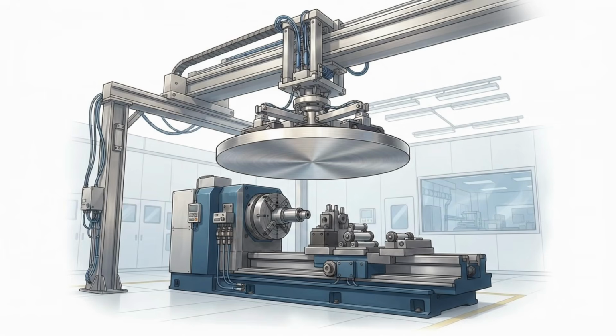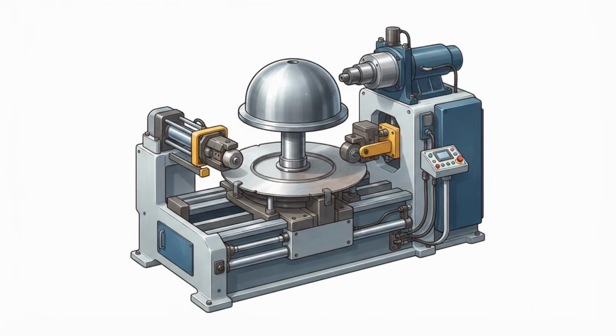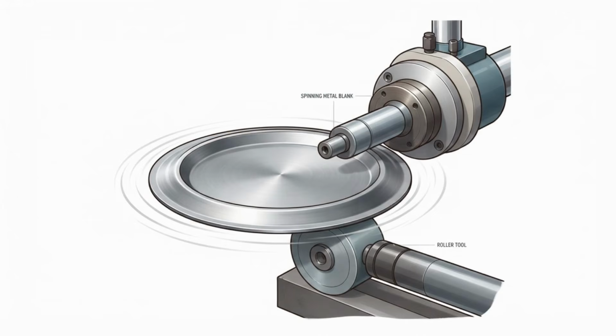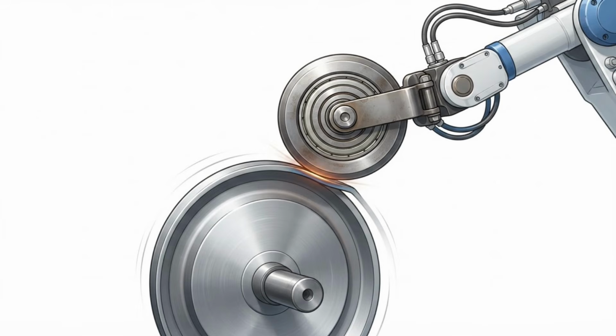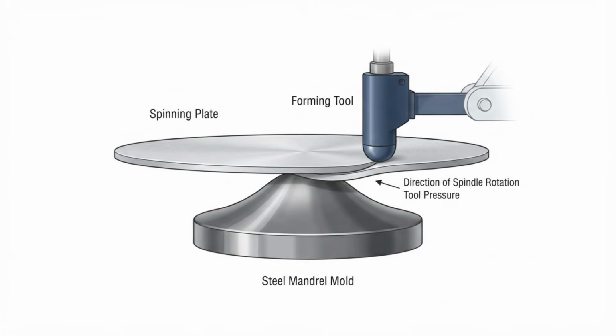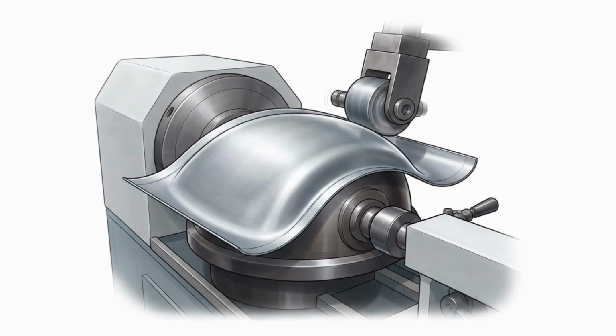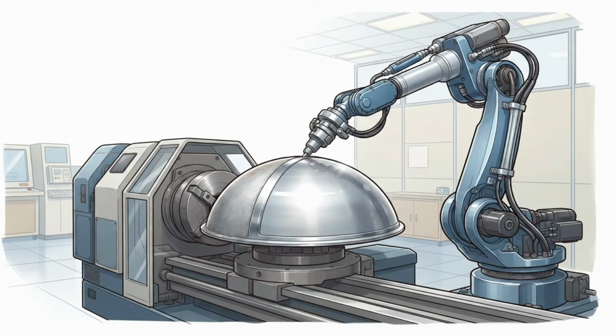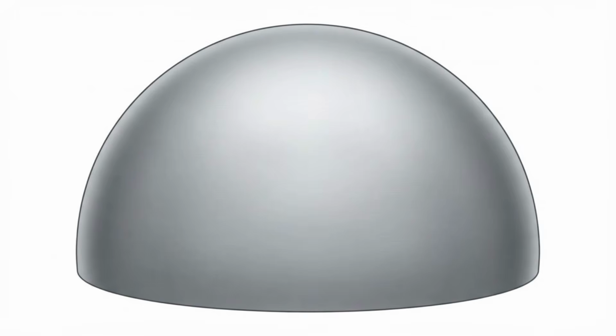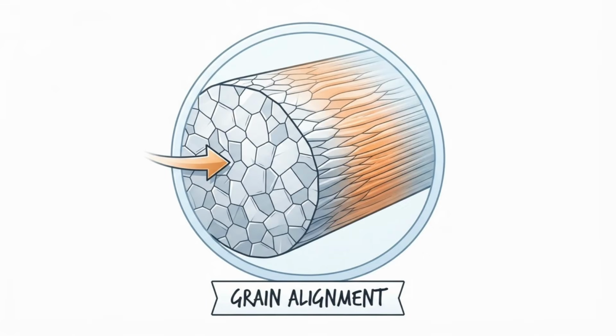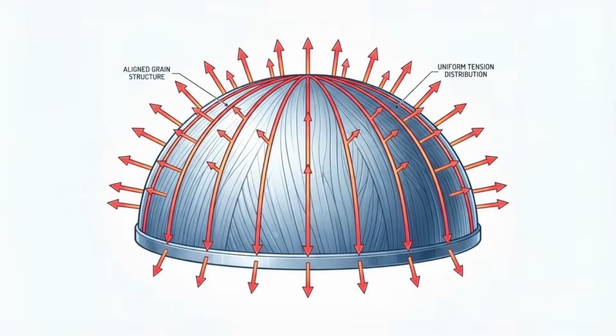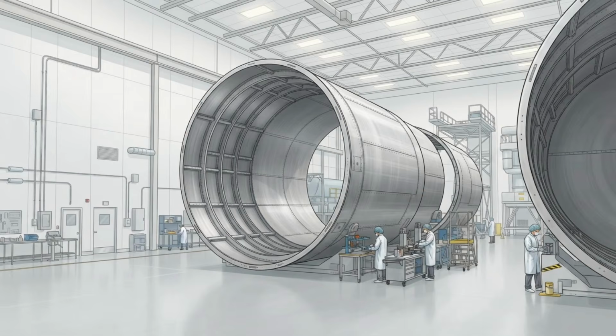The manufacturing of a tank dome begins with large, flat, circular plates of this alloy. These massive metal discs are placed onto a heavy-duty spin-forming machine. As the plate spins at high speed, enormous robotic rollers press against the metal, forcing it to yield and stretch over a curved mold called a mandrel. This cold working process shapes the metal into a perfect, seamless dome while simultaneously aligning its crystalline grain structure to drastically increase its tensile strength.